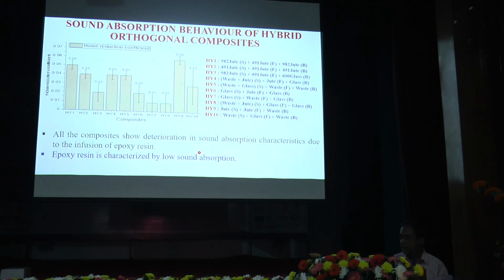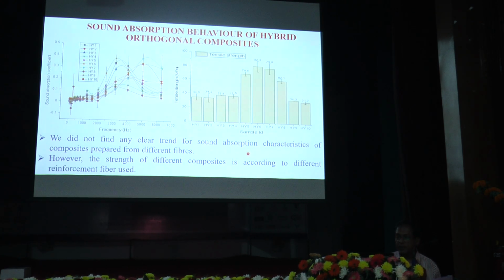This exists because in manufacturing this composite, we have used epoxy resin, along with epoxy resin we have hardener. Epoxy resin is basically made up of hardener and cross-linking agent. Due to the hardener and cross-linking agent, they have created a very complex chain-like bonding structure inside the material, and as a result there is very little option for acoustic absorption. So all of the material behaves erratically, and we do not find any consistent sound absorption coefficient.